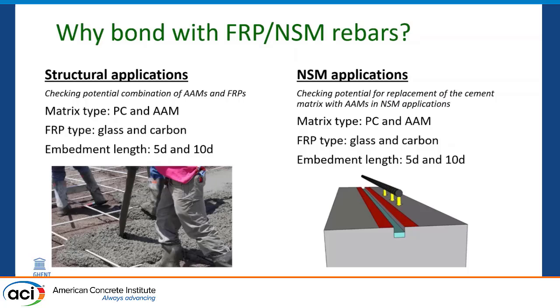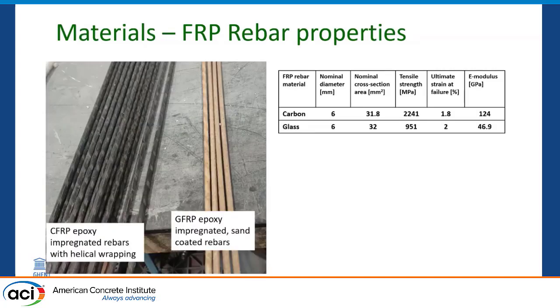We wanted to test the suitability of alkali-activated materials in structural application with FRP bars, and for that we used two matrix types, Portland cement and AAMs, two fiber types, glass and carbon fiber, and two embedment lengths in direct pull-out tests. For NSM application, we wanted to check the potential for replacement of the cement matrix with alkali-activated materials, and there we also used two matrix types, two fiber types, and two embedment lengths. We had CFRP bars of diameter 6 that are epoxy impregnated with helical wrapping, and for GFRP we had epoxy impregnated sand-coated rebars.